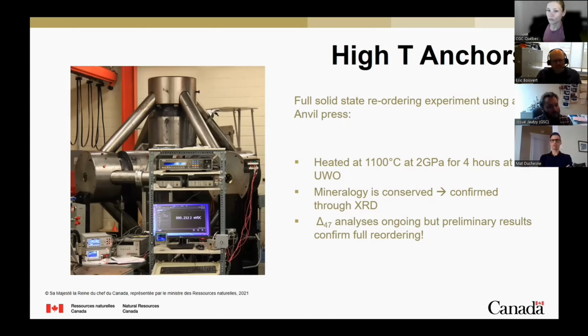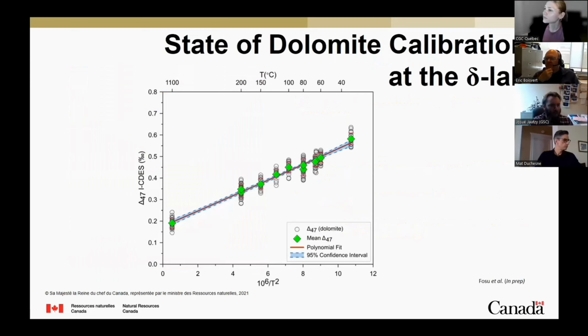We don't have this at the GSC, so we paired with very nice folks at the University of Western Ontario. They routinely do experimental petrology, so we're able to press and heat our carbonate to 2 gigapascals and 1100 degrees Celsius for 4 hours. Then we quench it down. We check the mineralogy again with XRD. We're lucky, it's dolomite, we're happy. And then we measure the Δ47, which is the clumped isotopic abundance. So that's the state of the dolomite calibration at the Delta Lab now.